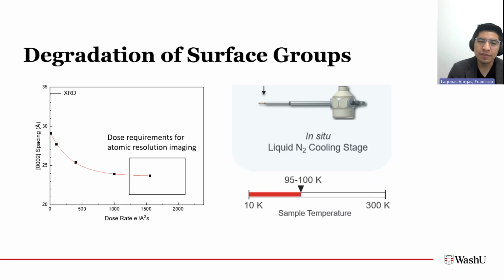And here, when we extend this data out into higher dose rates, we can begin to understand what we were seeing in some of the atomic resolution imaging. So once you put the sample into the microscope and you start exposing it to electrons, you see this exponential decay in the basal plane spacing. And this decay begins to plateau around the amount of electrons that we need for atomic resolution imaging. So earlier when I showed that we were imaging these at about 1,000 or 6,000 electrons per angstrom squared, we had already saturated this signal pretty far. And so that's why it looked like the MXenes were really stable, although they were already amorphized.